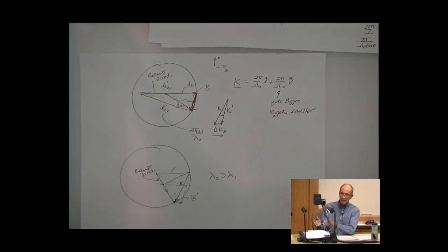when you reconstruct with one direction, you get a shorter wavelength. When you reconstruct with the other angle, you get a longer wavelength, okay? So what seems to be happening is that in your dispersion relationship, when you do a swelling, the efficiency curves move, if you think of the angle, towards each other or away from each other, depending upon whether you're shrinking or swelling that material. So the same kind of phenomenon is occurring with the wavelength.